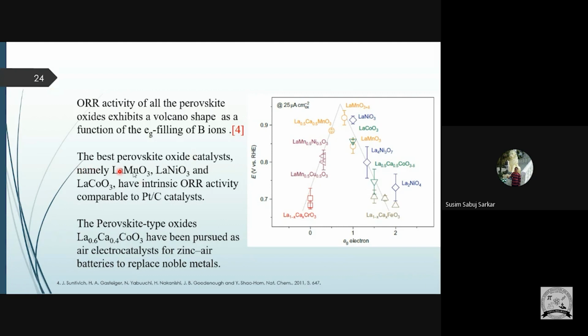The best perovskite oxide catalysts LaMnO3, LaNiO3 and LaCoO3 have intrinsic ORR activity comparable to Pt/C catalysts, so the activity of these three may be comparable with the platinum carbon catalyst. Perovskite-type oxides of lanthanum, calcium, cobalt and oxygen have been pursued as air electrocatalysts for zinc-air batteries, to replace the noble metal. They also show a significant amount of catalytic activity, so there we use the perovskite catalyst.